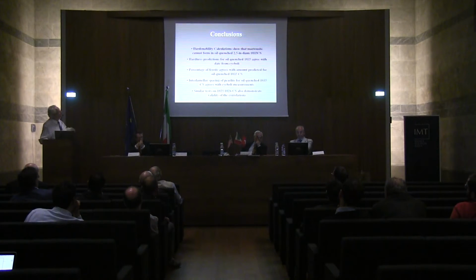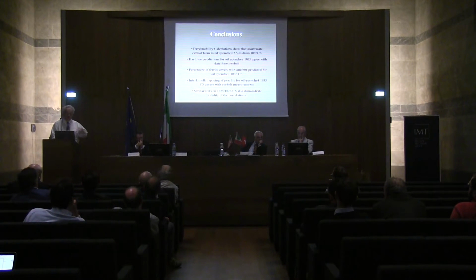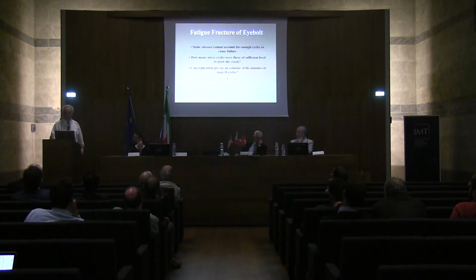So in conclusions, hardenability calculations show that martensite cannot form in an oil-quenched 2.5-inch diameter 1035 carbon steel. Hardness predictions for oil-quenched 1035 agree with data from the eye bolt. The percentage of ferrite agrees with the amount predicted for oil-quenched 1035. The interlamellar spacing of the pearlite for oil-quenched 1035 carbon steel agrees with the eye bolt measurements. And similar tests on 1025 and 1026 carbon steels demonstrated the validity of these calculations. We want to do extra tests to prove that this method works.